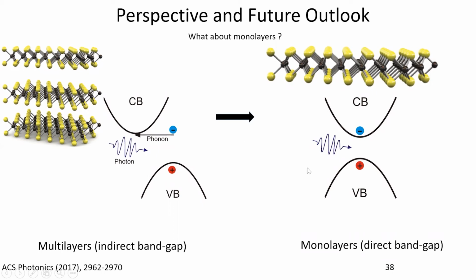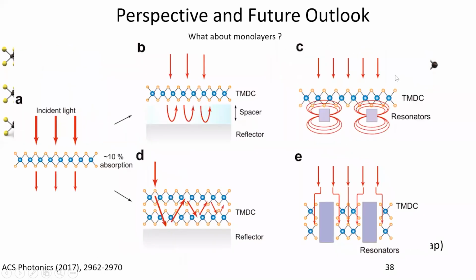The problem with monolayers is that trapping light becomes much harder when you have just less than 1 nanometer thick active layer. And we have proposed some strategies of how to trap light in monolayers. Of course, multi-layers I already showed you. We have also done some more cool work on multi-layers and light trapping in different ways that I'll briefly talk about. But then in monolayers, there are also strategies where you can start trapping light.